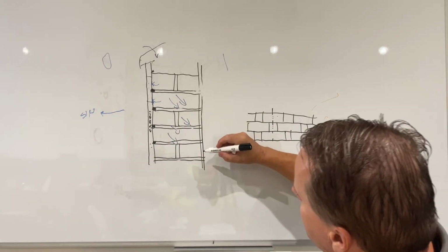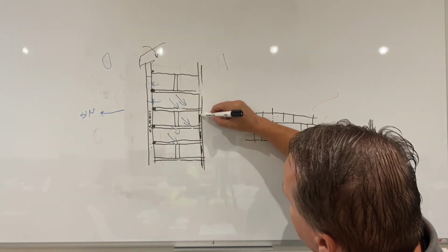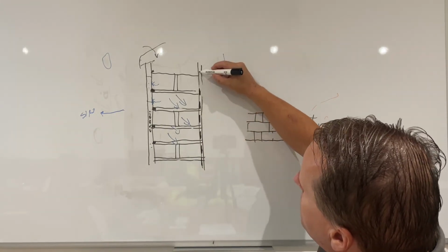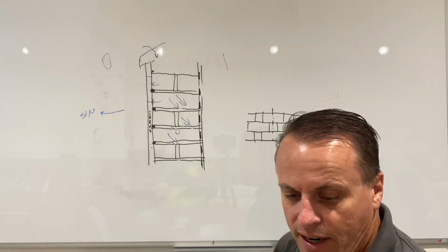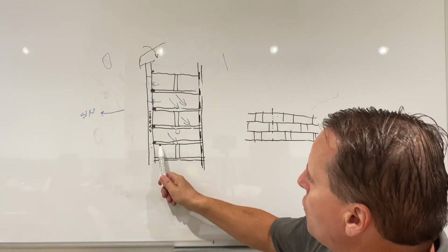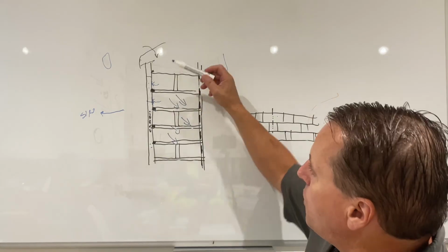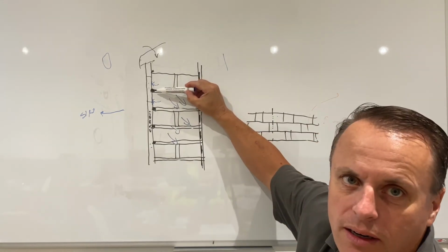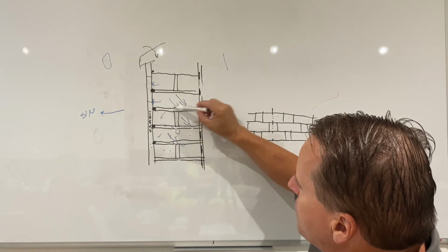So more moisture now comes into the wall. So what they've then done is they put this black bitumen coating on the wall on the inside of the property and rendered over it with a cement sand render. So all they've essentially done in trying to do this, they've done 1 wrong, 2 wrong, 3 wrongs, 4 wrongs, all trying to correct what all they needed to do first time around, which was repoint in lime mortar. So this whole wall is now absolutely saturated.